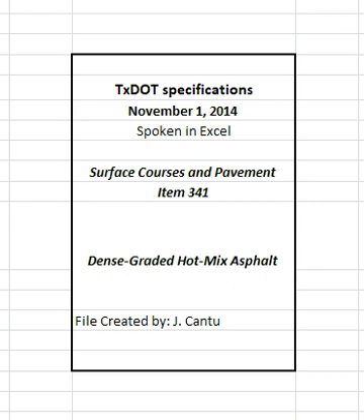The aging ratio is the DSR value of the extracted binder divided by the DSR value of the original unaged binder. Obtain DSR values in accordance with AASHTO T 315 at the specified high temperature performance grade of the asphalt. The engineer may require removal and replacement of the defective material at the contractor's expense. The asphalt binder will be recovered for testing from production samples or cores in accordance with TEX 211F.